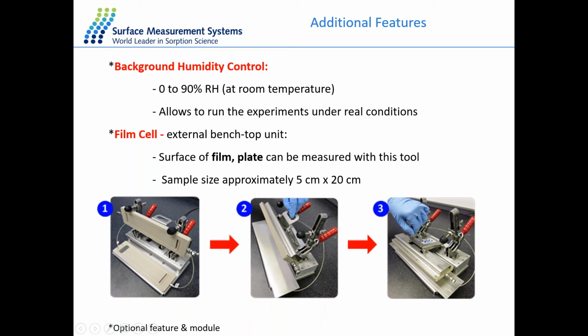linked to the IGC-SEA where your columns would go inside the door. And your probe molecules would be injected along this panel here. In this case, you need a sample that's big enough to cover this space. And because this film cell would sit beside the IGC-SEA, you may not necessarily have the temperature control, but you will have the humidity control, and you will be able to carry out exactly the same experiments.